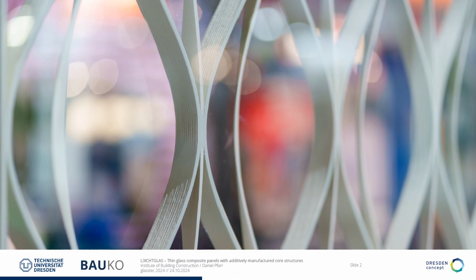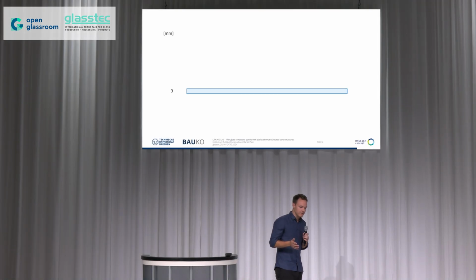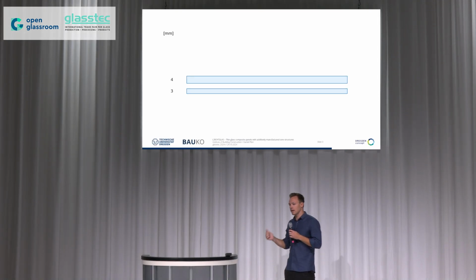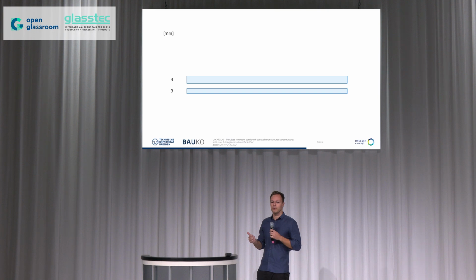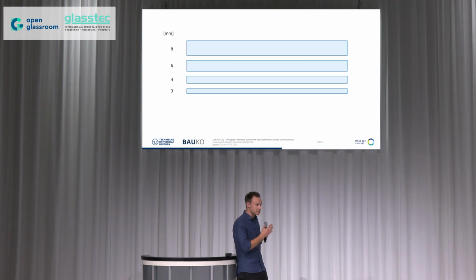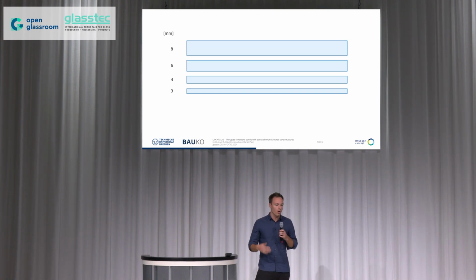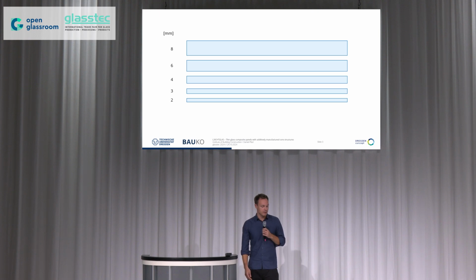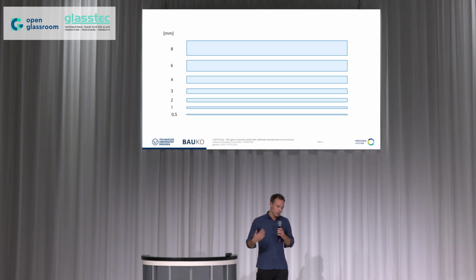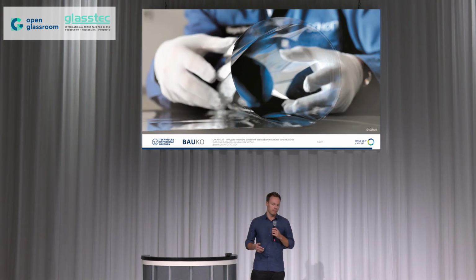It shows a thin glass composite element, so two very thin sheets of glass glued to a 3D printed core structure. But why would we use thin glass? Well, actually we are starting using glass with a thickness of 3 or 4 millimeters, but even 6 or 8 millimeters are much more frequently used in practice. And we would like to leave this comfort zone and use 2, 1 or even 0.5 millimeters.